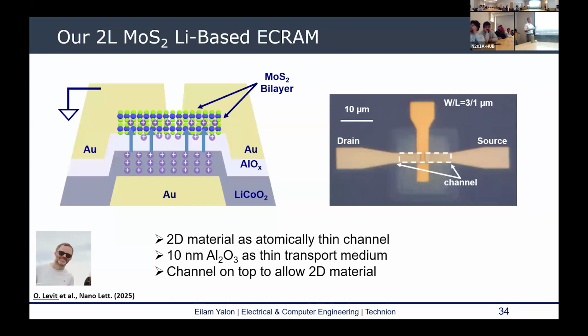There are some details here, and we tried various configurations, but what worked for us eventually was, for the so-called electrolyte, we just used a thin aluminum oxide film. So it's not really an electrolyte by definition, it's just a very thin film. And then we used lithium as the mobile ion, and we introduced this reservoir or source of lithium. In this case, it's lithium cobalt oxide, which is conducting, in this part of the gate stack. So this is what worked for us. For the 2D channel, we're using a bilayer MoS2, and it's on top for processing issues. We didn't want to sputter on top of the 2D layer. So this is our device structure. There is a whole lot of source-drain to gate overlap.